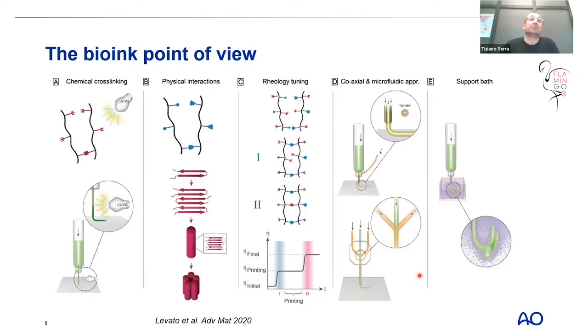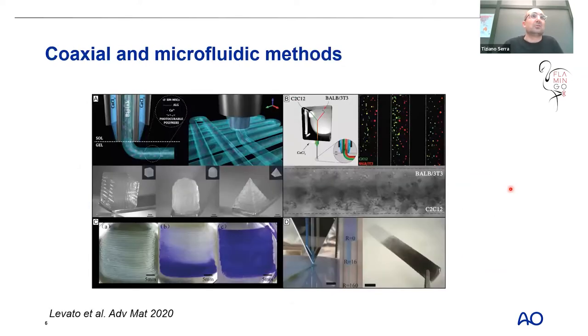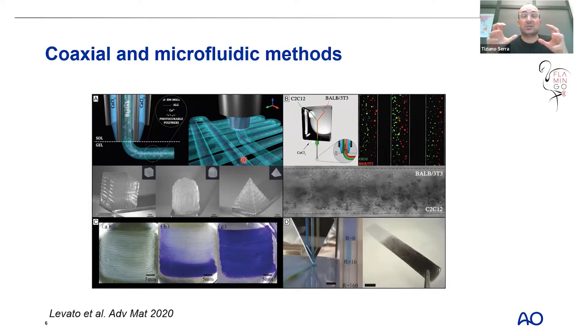Other opportunities are in the field of connecting this extrusion system with microfluidic or coaxial printing, which allows cross-linking of the bio-ink solution through merging with cross-linking solution. In coaxial printing, the bio-ink flows out and is cross-linked through a coaxial solution of calcium chloride, helping the gel retain its structure and maintain the structural stability of the construct in many different shapes.